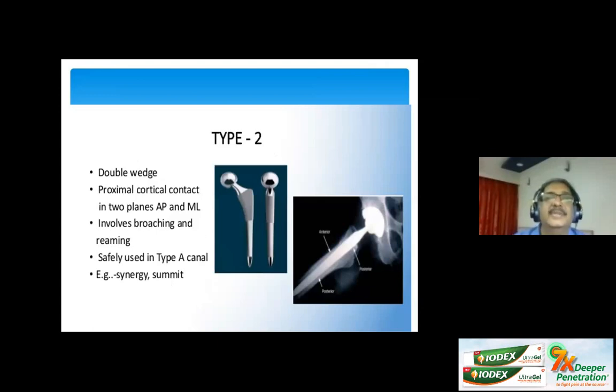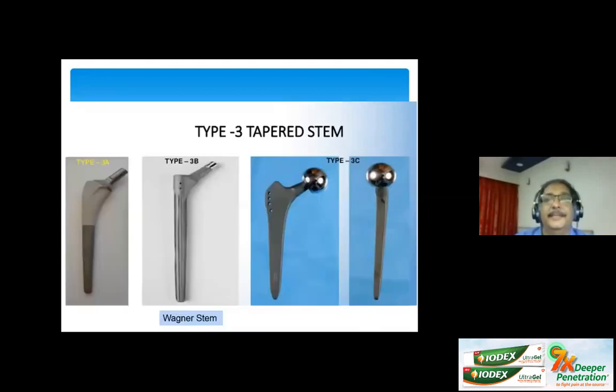Type 2 stems are the double wedge stems with proximal cortical contact in both AP and mediolateral planes. These can be used quite well in the Dorr type A femurs. They do involve broaching and reaming, and the Summit by DePuy, an excellent stem, is also an example. The Synergy by Smith and Nephew also fits the same criteria.